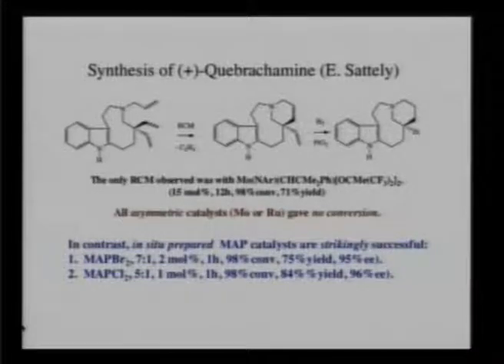But these MAP catalysts, like the one I just showed you with the dibromide ligand, as a diastereomer, actually as a mixture of diastereomers, works very well. 2 mol% or 1 mol% in the case of the dichloro ligand. 1 hour, 98% conversion, good yields, and very high ee. So this is surprising. We reported this back in 2008.